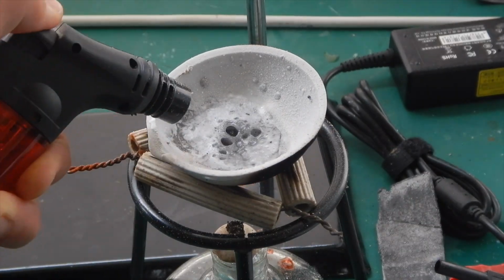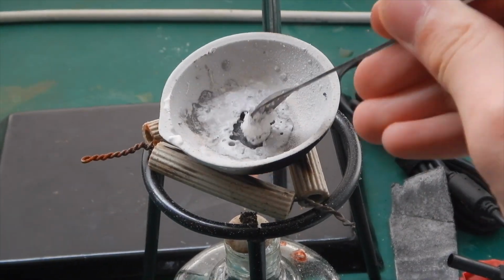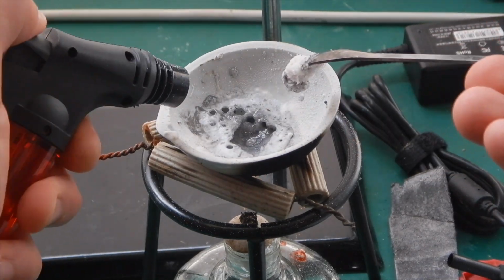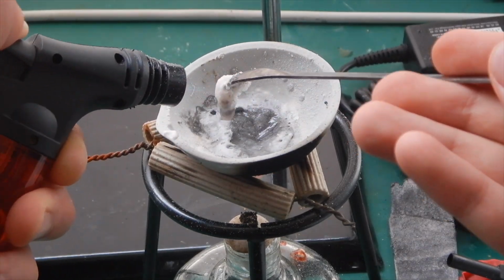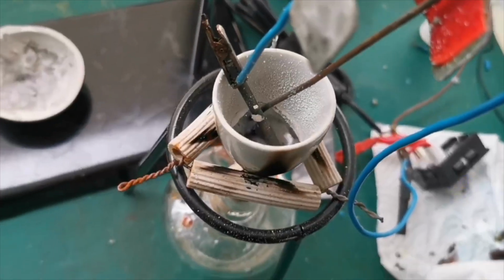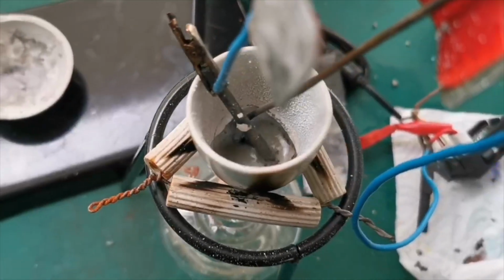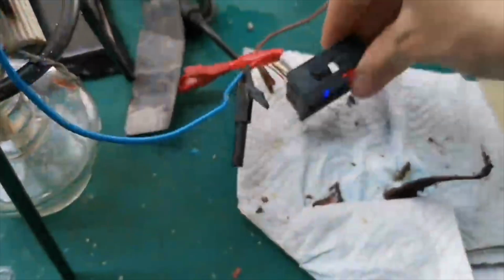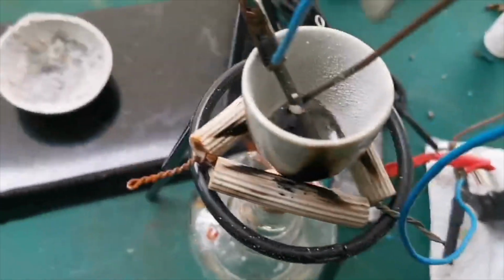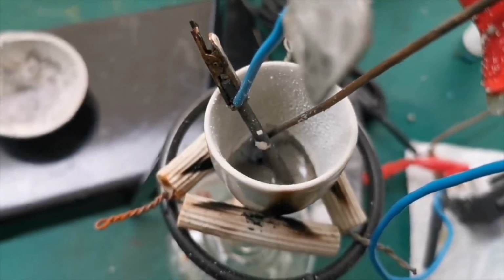Because the salt solidified and I cannot get it to melt again, I decided to do the electrolysis in a crucible. Because the crucible is a lot smaller, it should retain heat a lot better. And it seems to go quite well. The current was 1.88 amps, far better than what we got before.